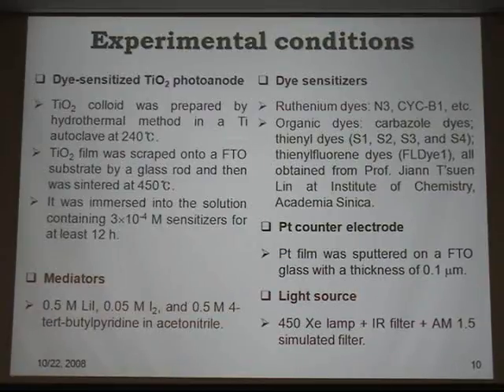Experimental condition is pretty much the same as that we found in literature, except here we try to use different dye, and counter-electrode is platinum, which was sputtered on FTO glass. Now the dye I'm going to talk about is two kinds. One is ruthenium-based commercial dye, and the dye called CYC-B1 dye, which was synthesized by my co-worker, and organic dye, the one that I mentioned, was synthesized by Professor Lin at Academia Sinica. This is the organic dye, and this is the inorganic ruthenium-based dye.